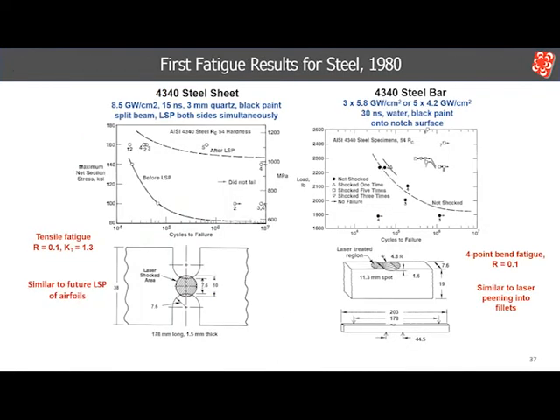The fatigue properties were examined in 2 configurations, steel sheet and steel bar. In laser peening thin sections, where fatigue cracks generally occur at an edge, the laser peening would be applied along the edge where a crack could occur. The shock wave travels through the sheet, producing a compressive residual stress through the thickness. In this case, the compressive stress on the crack is relatively constant as it propagates into the laser peened area. On the right is shown laser peening into a notch in a beam.